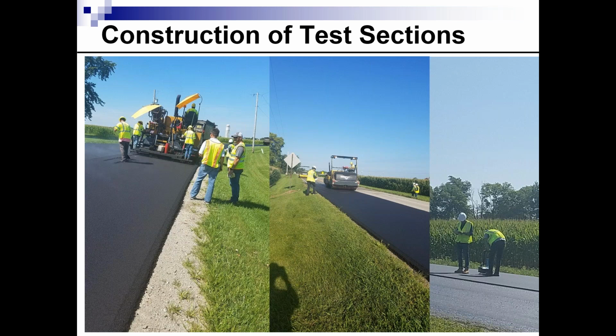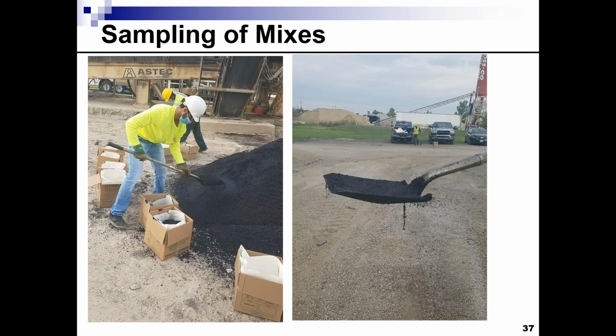We took density measurements just to make sure that the density was consistent, and we monitored the mix temperature, and made sure that all construction was done as the specification requires. We also took samples at the asphalt plant as well as at the site. We wanted to make sure that we get samples that are representative of the mix. So we took big piles during production, and made sure the sampling was done such that representative samples of the mix were obtained.